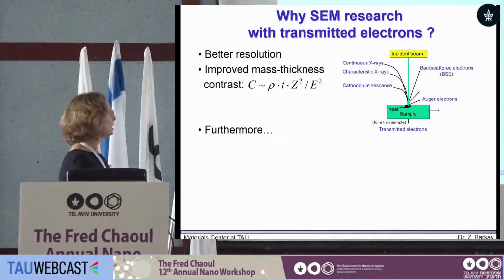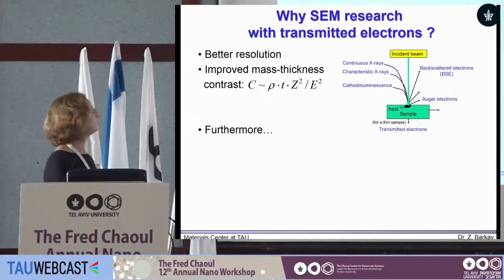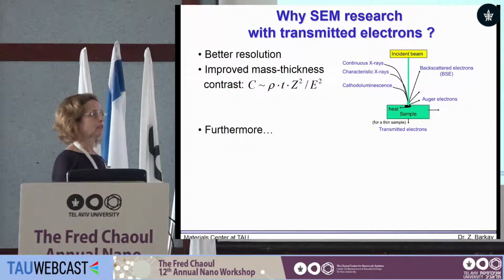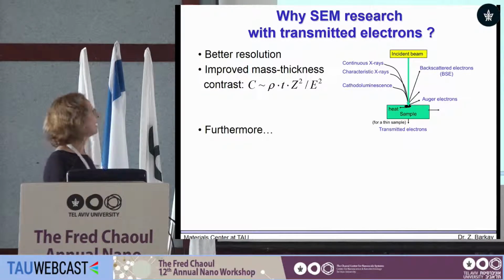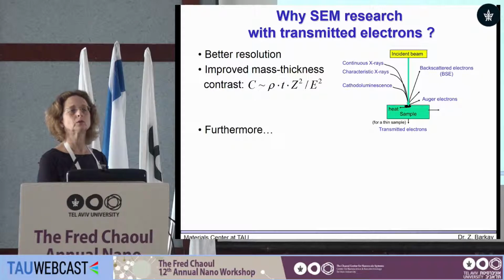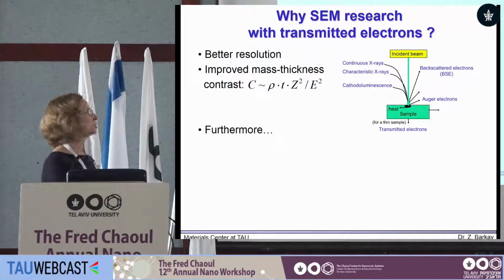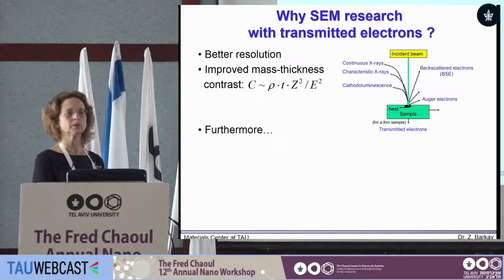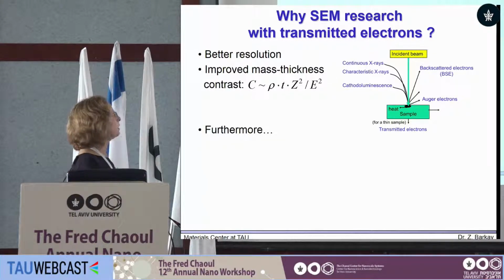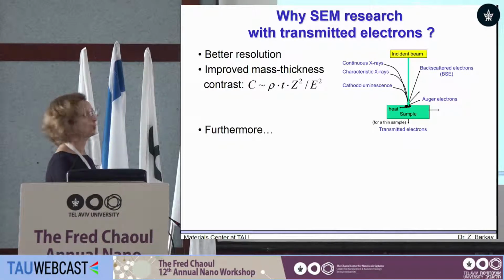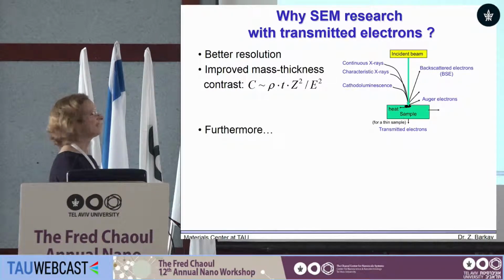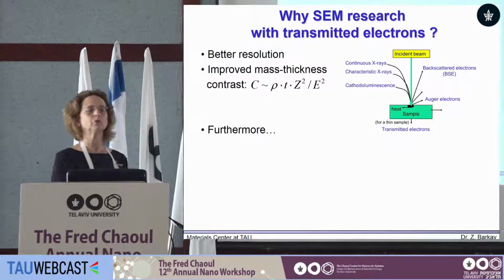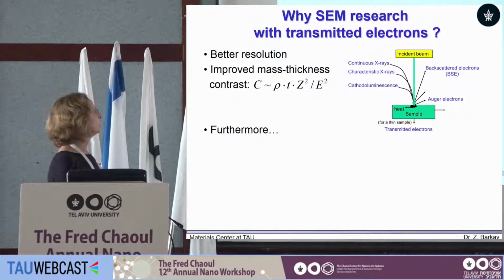What is not less important is the issue of contrast, because in amorphous, non-crystalline materials, we have mass thickness contrast in the bright field or dark field images. If you look at this simplified equation for dark field, you see contrast depends on the energy of the beam and on the atomic number. So when working at low energies, like in the SEM relative to conventional TEM, we actually get better contrast, and this is particularly important for low atomic number material like biological materials and soft materials.